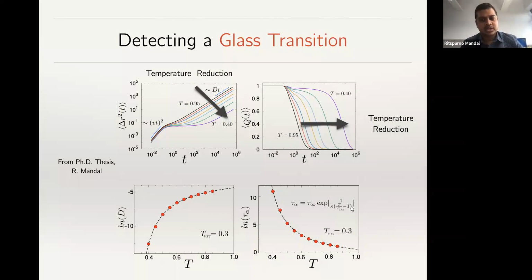There are some other materials which don't behave like this, or you can think of them as Vogel-Fulcher-Tammann forming material, but the corresponding temperature is 0. And these are known as strong glasses. So most of the glassy materials that we see have either strong behavior or fragility. Typically the network forming glasses like silica, the window glasses, are strong glasses. They don't form Vogel-Fulcher-Tammann. But then there are other glasses, colloidal glasses. They follow this.